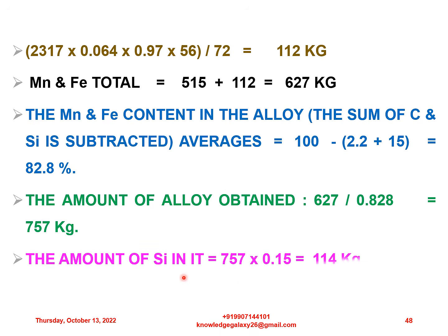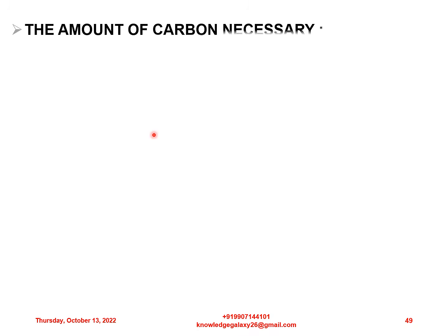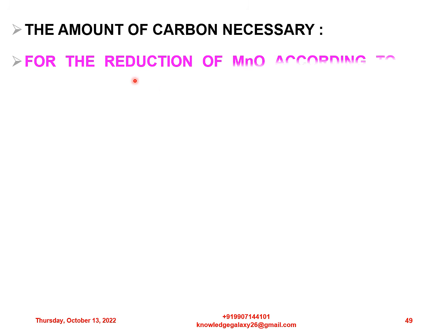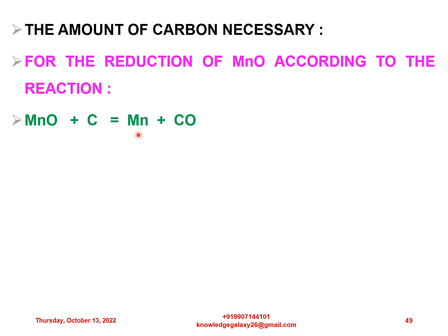The amount of silicon in it is 757 into 0.15 is equal to 114 kg. This 0.15 is the 15% silicon in the alloy. Moving on, next is the amount of carbon necessary. Here I am going to describe how to calculate the required carbon. For the reduction of MnO, according to the reaction MnO plus C is equal to Mn plus CO, 515 into 12 divided by 55 is equal to 112 kg.